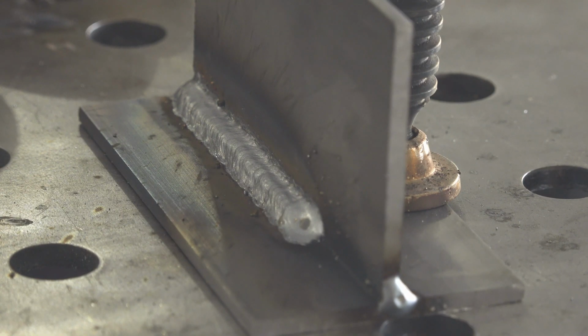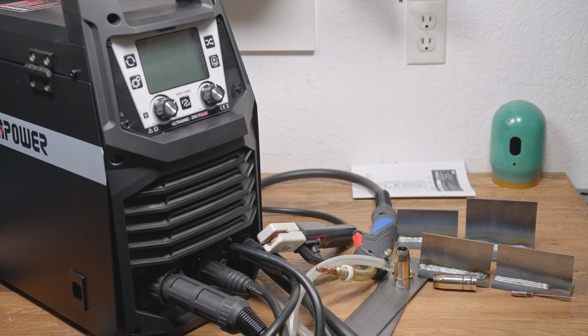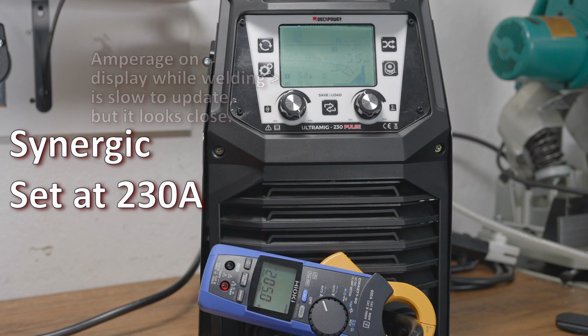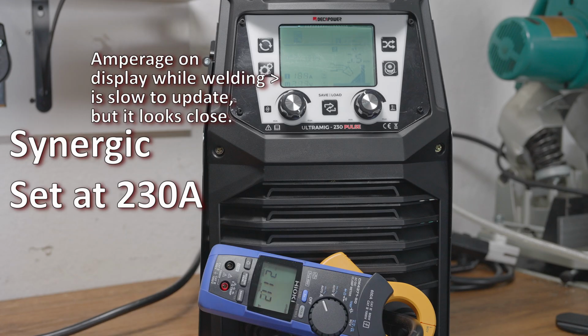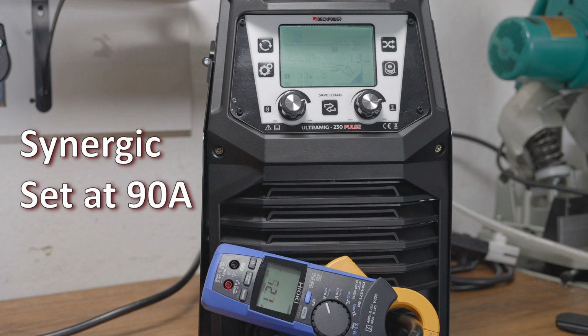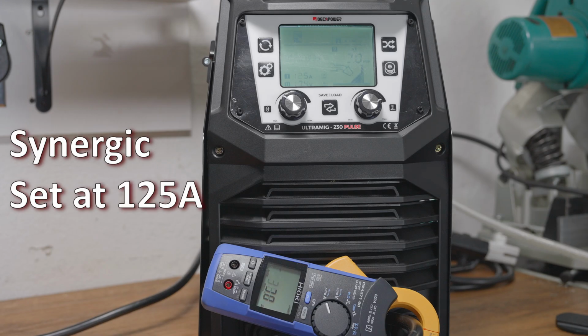In normal MIG mode, I found the synergic tuning pretty good. I could turn the amperage to any setting and just weld. It ran pretty smooth without any tweaking. In synergic mode, with the machine set at 230 amps, it put out closer to 210 amps. At other settings, it also tended to output a bit less amperage than the setting. MIG is a constant voltage process, not constant amperage, and it wasn't terribly far off, so it's not that big of a deal as long as you're aware of it.